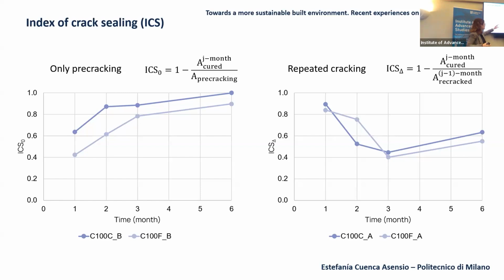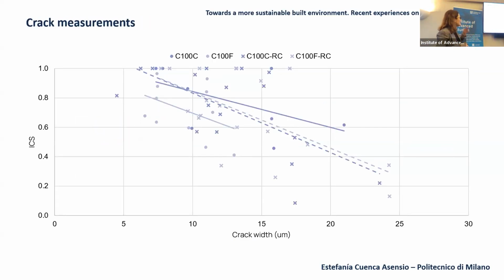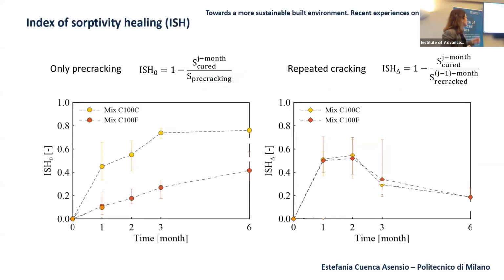And as you can see, this is quite interesting also because after 1 to 3 it is obviously decreasing, but then we have a slight increase. Why? That's because we have 3 months occurring, not such a short period of cracking and healing. Well, this is another perspective of the same mixes. We have the index of crack sealing compared to the crack width. Obviously, self-healing behavior is better when the crack width is very thin, and the index of crack healing is lower when the crack width is higher, as expected.